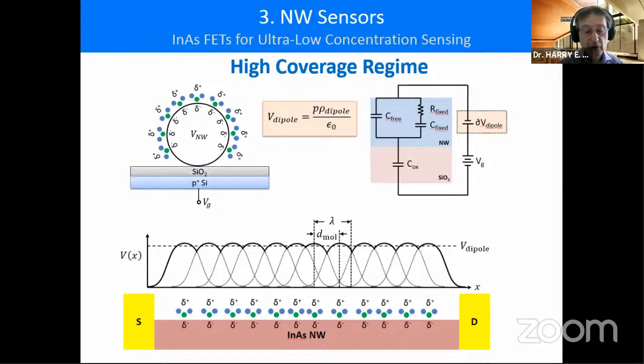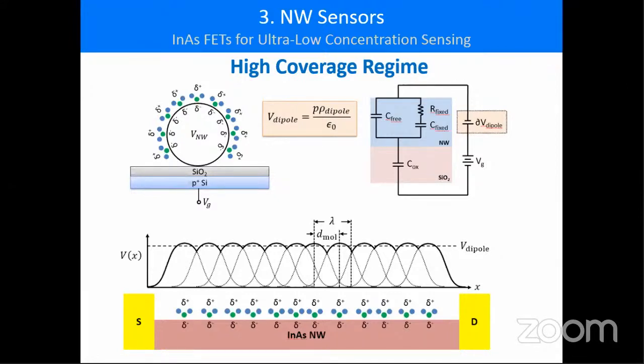a continuity equation with the density of states appropriate for the surface states in there, and their occupation, using obviously detailed balance. It's also got in it the equilibrium distribution of charges and so forth, the charge neutrality condition, and a proper Poisson type of analysis of the potential in these systems. And with that, you can recover a lot of behavior.